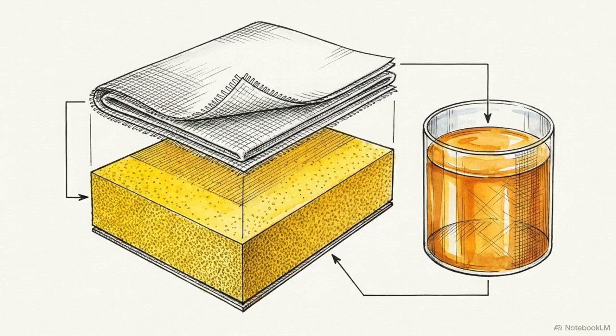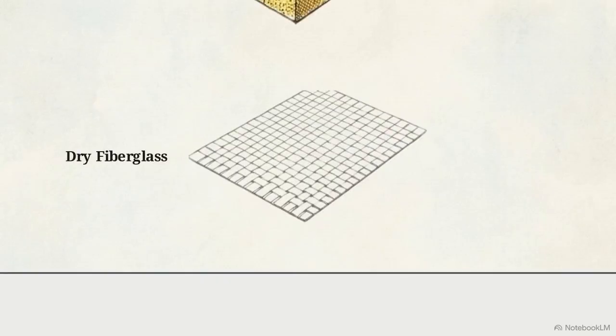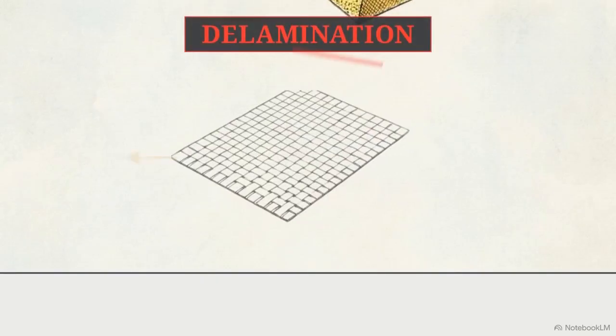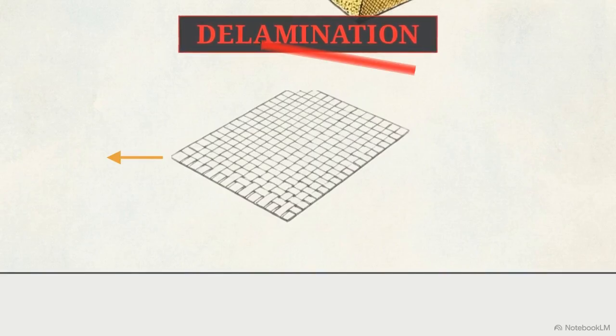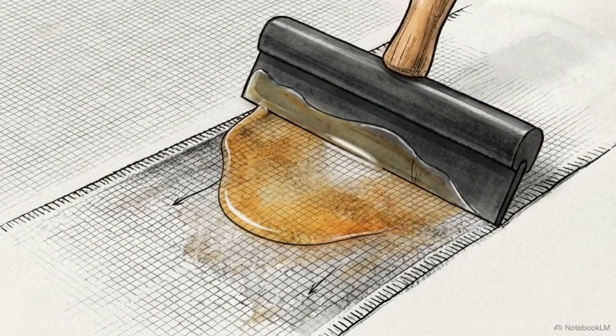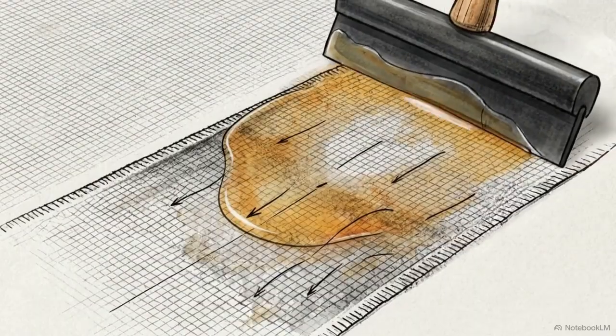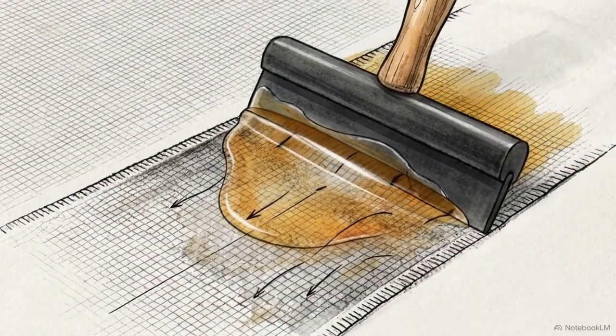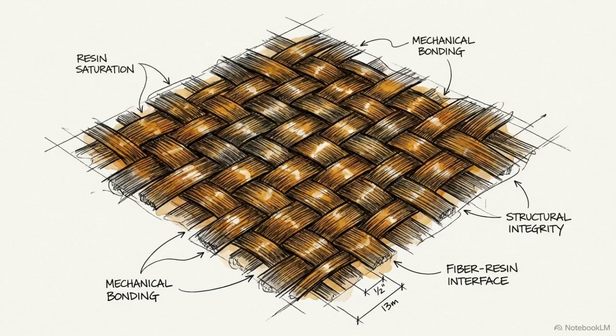Getting those layers to function as one requires a precise fabrication process. If you place a dry PVC core onto a dry or partially wet sheet of fiberglass, the layers will peel apart and delaminate the moment they are put under a load. To prevent that failure, fabricators use mechanical force to drive liquid epoxy resin deep into the weave of the fiberglass. You have to use a roller or a squeegee to ensure the resin fully saturates every individual fiber.